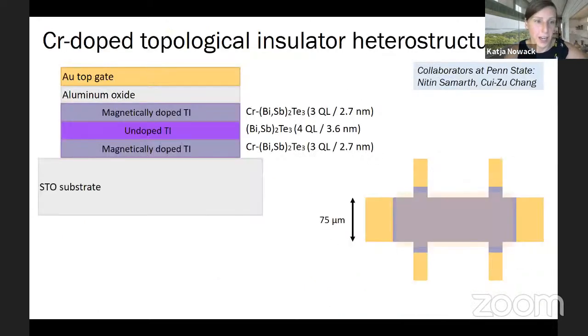All right, we are looking at one material system that realizes the quantum anomalous Hall effect, and in our case, that's chromium-doped topological insulator heterostructures. This is in collaboration with Nitin Samarth's group and Cui-Zu Chang's group at Penn State. That is the structure of the heterostructure that we look at, and this film is patterned into a fairly large Hall bar that is about 75 micrometers across, and maybe 100 micrometers long between the voltage probes. It also has a top gate, in this light yellow shade.